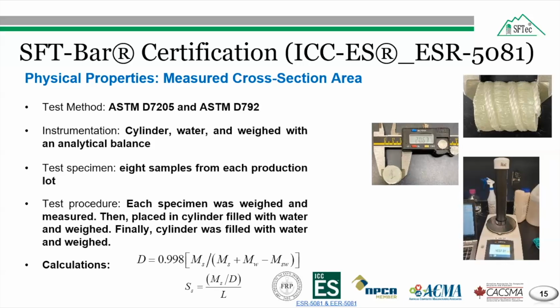The cross-sectional area of the specimen in square millimeters was calculated using the second equation, where D is the density of the specimen and 0.998 is the density of the water at room temperature. MS is the mass of the specimen, MW is the mass of the water in the cylinder, MSW is the mass of the water and specimen in the cylinder, and L is the length of the specimen.